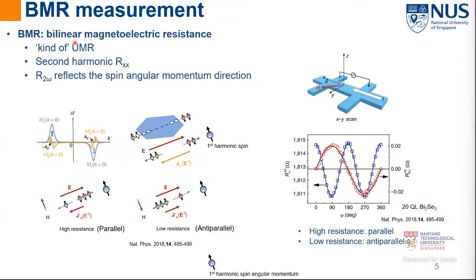BMR is short for bilinear magnetoelectrical resistance, which can be seen as a kind of UMR, but the difference is that the amplitude is linearly dependent on both current and field. The second harmonic Rxx from the BMR measurement can reflect the spin angular momentum direction. Why? Here I will give a short explanation. For positive charge current, the first harmonic spin angular momentum will generate from the minus k space. However, the second harmonic current will generate both from the k and minus k spin. When there is no external field, the k and minus k spin are at the same amount and they move in opposite directions. Hence, there will be no equivalent current.